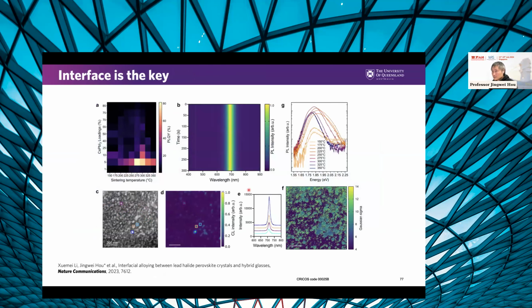Because the chemical information, the structural information, and the property information across the composite is so rich, we can't help studying the properties of the composite. We want to understand what the best composition is, and what the best sintering temperature is within the composite. So we identified that if we put in 5% and sinter at 300 degrees, it seems we can get the maximum brightness.